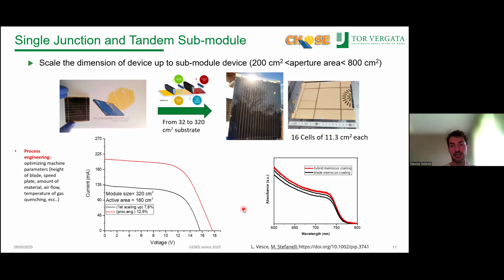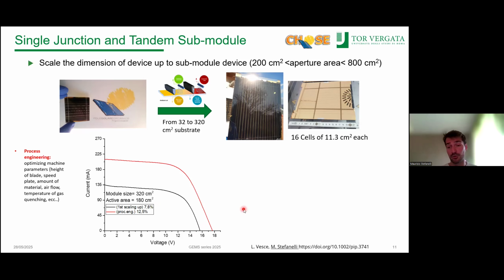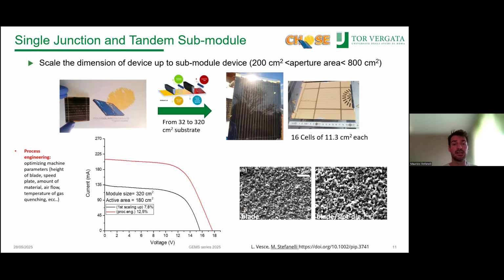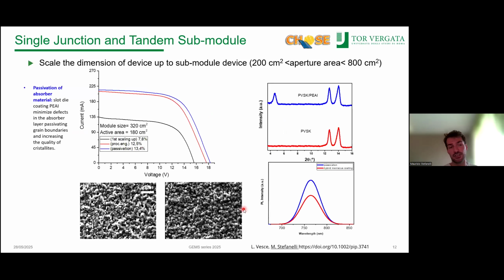We also characterized this optimization from the optical point of view and the morphology point of view. The next step was implementing the passivation on top of this material. We used phenethylammonium iodide as a reference passivator that enables the formation of 2D perovskite on top of the 3D perovskite, passivates the grain boundaries and boosts our VOC. With the passivation strategy, we got the best efficiency around 13.4%. We also assessed the presence of the 2D perovskite on top, and we see the passivation effect of our PEAI molecule on top of our perovskite.